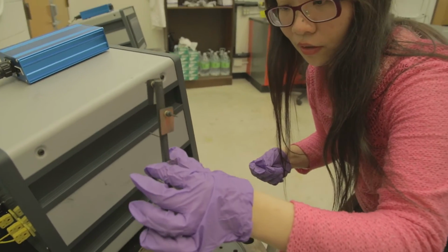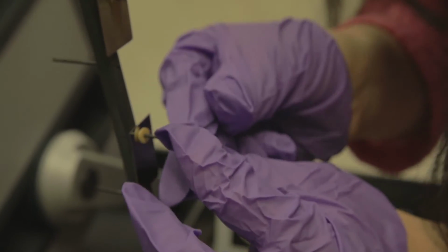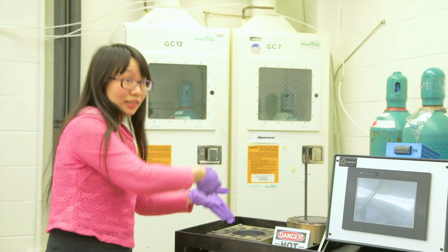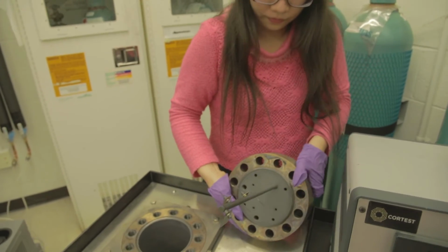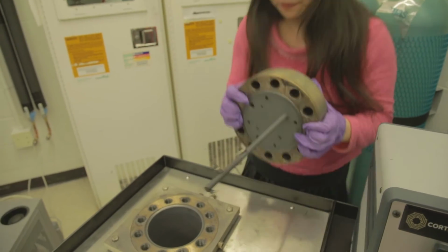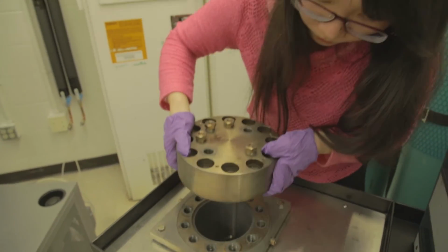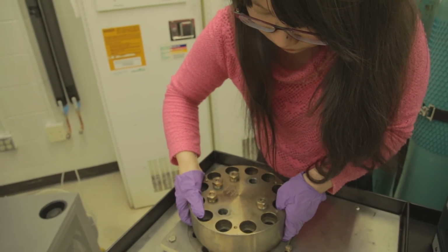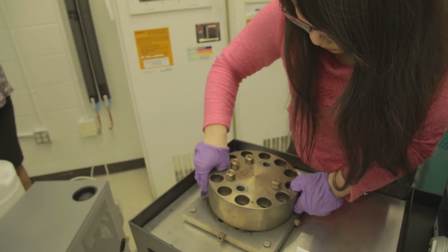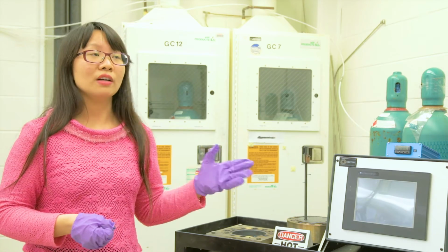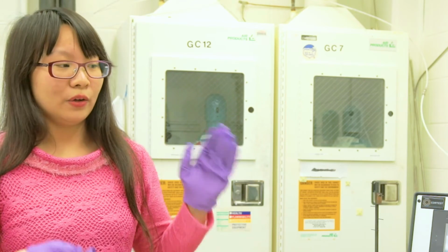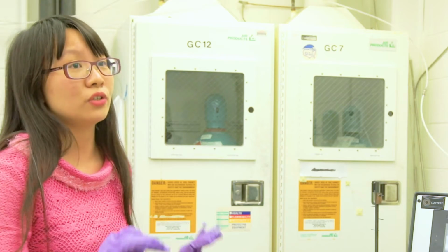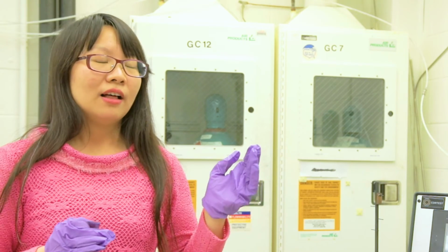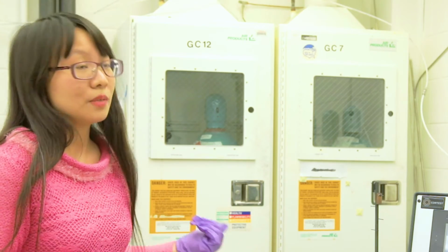This is one of the samples we have. As you can see, it's very shiny because we did some sample preparation, and we put this sample on this tree. And we will flip this head into the autoclave. And these two are static autoclaves. They are very similar to real reactors, but just on a small scale. The temperature can go very high, around 325 degrees C, and the pressure is 2,500 psi. And there are two autoclaves because we want to separate different water chemistry solutions. One would be lithium hydroxide, and the other is potassium hydroxide.